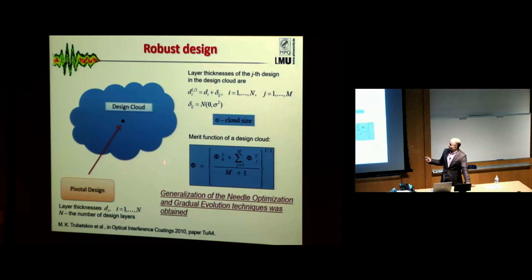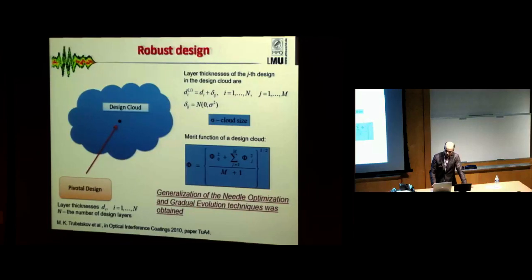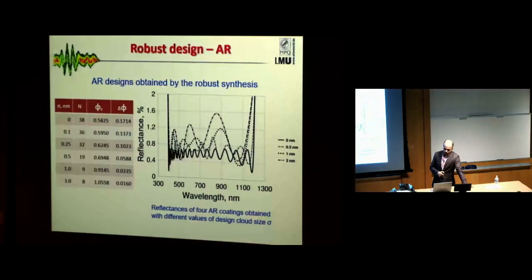Usually you have a merit function, and people usually consider only one design when they do this. But to make a more robust design, we consider a cloud of designs. It means we consider 50 or 100 designs at the same time. By applying this algorithm, we are able to stabilize our layer structure significantly. It's one example, an anti-reflection coating. It's a very good example because here I have the precision that we have.